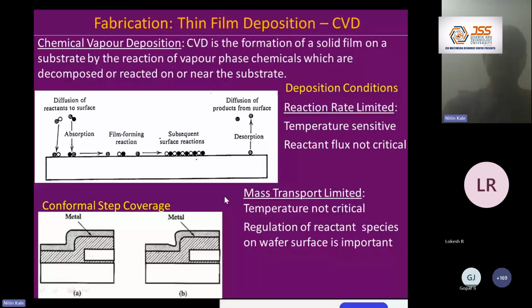Then you have thin film deposition. The difference between growth and deposition is that in growth the substrate is consumed, in deposition the substrate is not consumed. The species in the gaseous phase come, sit on the substrate, react, and form a film on the substrate. For example, you can have a silicon nitride film. You have silicon as the substrate, you have silane as the incoming gas, which gives you silicon, and you have ammonia, which gives you nitrogen. So silicon and nitrogen bond to form silicon nitride at that temperature.